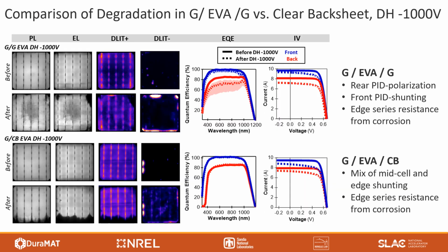So now I'll zoom in to look at a couple of the most interesting comparisons. Here I'm showing the glass-glass EVA compared to the glass-clear backsheet EVA under negative bias damp heat. In both cases, we're seeing that shunting type change in the IV curves, which is that typical process of sodium ions diffusing from the glass to the cell under negative potential, causing those local shunts.